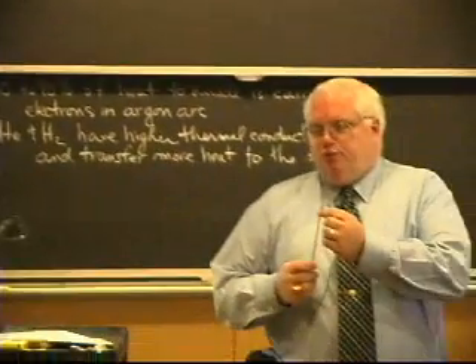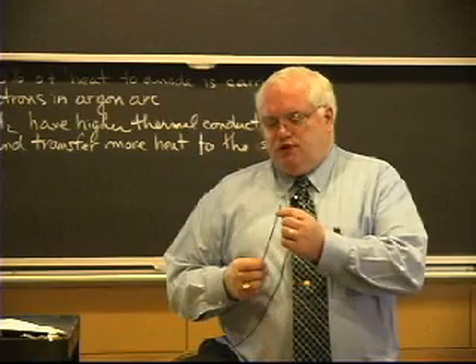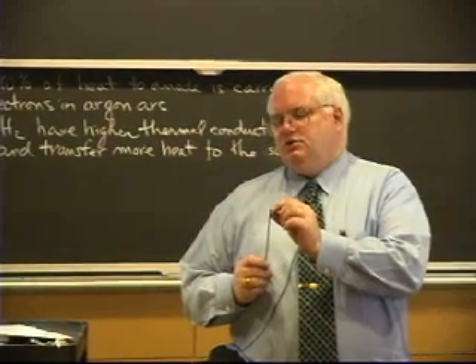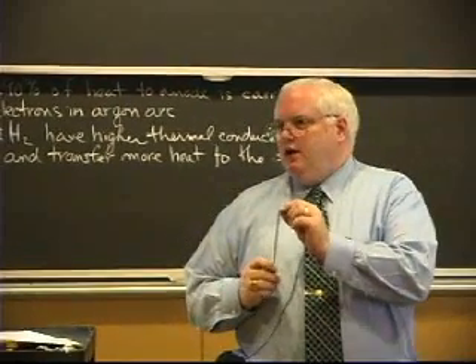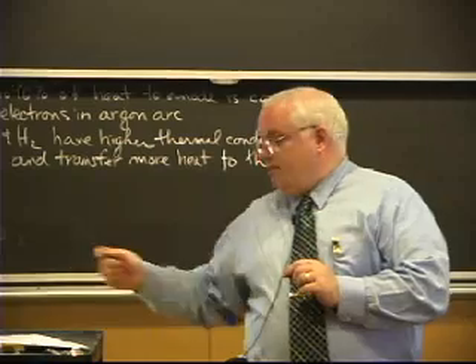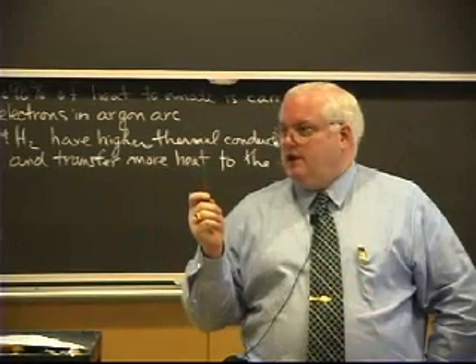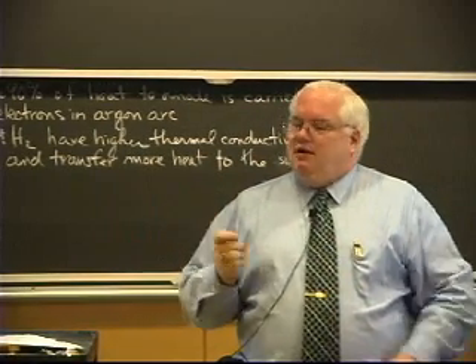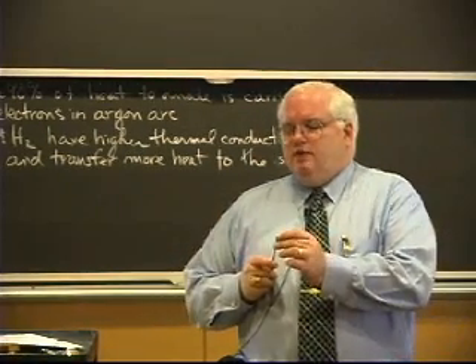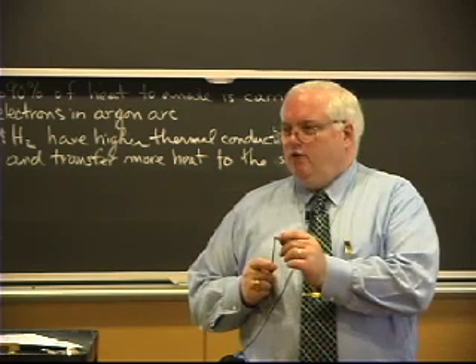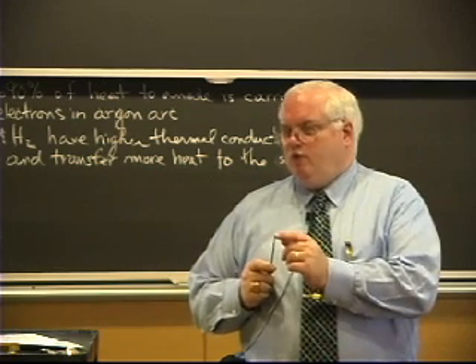I got off on this little radiation, and I forgot to tell you why we were talking about radiation. The thoria has a little bit of radiation, but it's thoria. It's thorium oxide. You can buy 1% or 2% thorium oxide powders, and basically it helps with electron emission. The electrons are coming out of the cathode. The tungsten electrode is the cathode, and it turns out the cathode voltage drop in tungsten is going to be 4 or 5 volts.